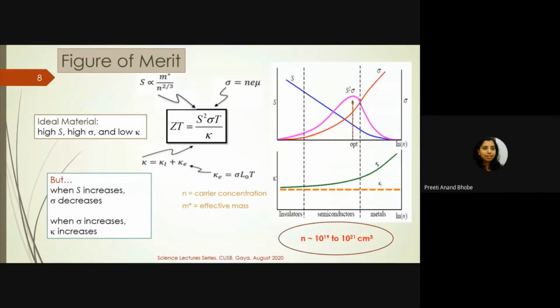So what people found was that if I plot on the x-axis the carrier concentration, and on the y-axis the Seebeck coefficient S, or the electrical conductivity, or the thermal conductivity K in the lower panel, and see how these values change with carrier concentration, represented here as log n, then one sees that the Seebeck coefficient, the blue line, decreases as the concentration of electrons increases.